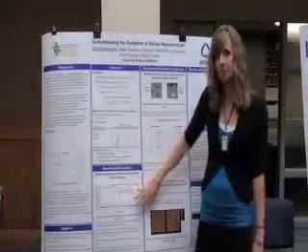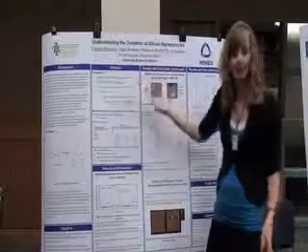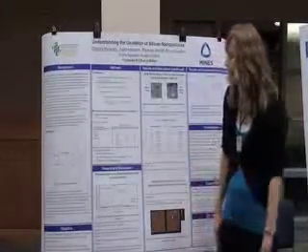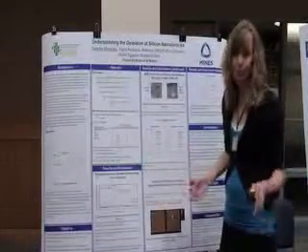Some of the interesting results, I won't go through all of them, but we found that photoluminescence shows us that the particles are actually being oxidized just by the washes. So we're using dichloromethane and ethanol to transfer the particles from toluene into a solution like ethanol that doesn't react with acids. But we found those washes are actually oxidizing our particles, which is not advantageous because our particles are already really small. They're like 3 to 8 nanometers, and so we don't want them to get too much smaller.